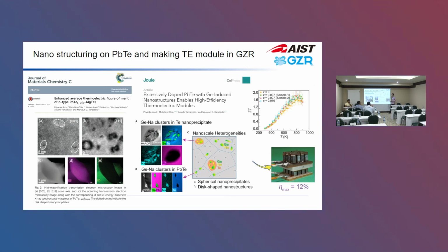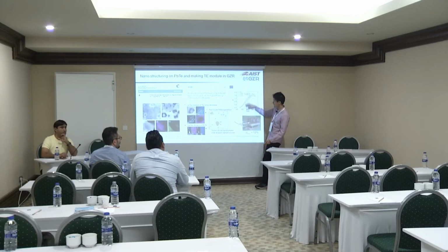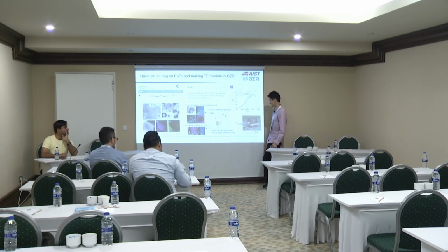Why then do you use the cascade model? Because this material is good for high temperature, but for the lower temperature, you need another material to cover the lowest part, so that you can have a high average ZT for the entire temperature range. I see. Because if you use it for just 300 Kelvin, it's going to be really small. So the temperature goes lower as you go down, right? Okay. So probably some temperature profile can be estimated. But they are going to produce different voltages from the top and bottom. How are you going to balance them? Yeah, I think they just use some electronic circuits. I see. Okay, thank you very much.